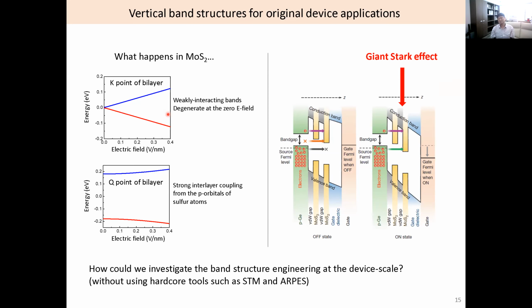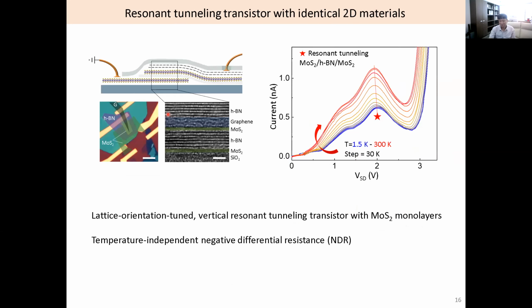But it was just from my curiosity, how could we study? So Shoujun Zhang, now he left our group, he and I thought about some MoS2 device. This is one example. Here we have monolayer MoS2 and several layers of hBN. This is a 2D insulator. And then we have this MoS2 monolayer. But the important thing here, two MoS2 monolayers, they are from one body. One body means we tore the MoS2 flake, and we keep the orientation of the lattice and we put this MoS2 heterostructure. So we have lattice orientation matched MoS2.